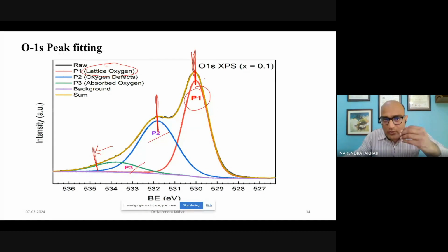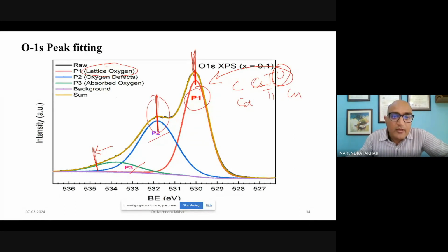Means the oxygen which is sitting there with the lattice, means CCTO. So this is what oxygen is, lattice oxygen. So this peak P1 at the lower energy side tells us that the oxygen is having bonds with this calcium, this titanium and this copper. This P2 peak is oxygen defects, and this P3 peak is the absorbed or chemisorbed oxygen.